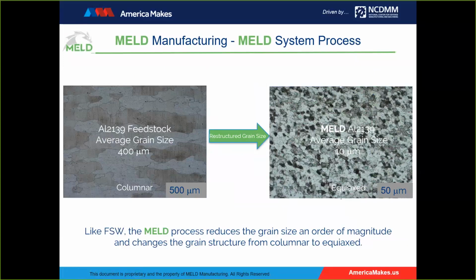The whole process is based similarly to friction stir welding. The process restructures the grain size by an order of magnitude. So on the left here is our 3/8 inch square bar feedstock of aluminum 2139. It has an average grain size of about 400 microns. After we deposit the material, the average grain size reduces to around 10 microns. So from 400 to 10 microns, more than an order of magnitude reduction in grain size. And all those metallurgists and technical fellows love grain size technology and so forth. So we really reduce that, and go from a columnar to an equiaxed structure and strength. So we have strength in all three directions, similar to what's been established for friction stir welding over the last 2 decades. But it's the same with the MELD process, because again we're using the same type of friction forces in the forms of torque and linear force.